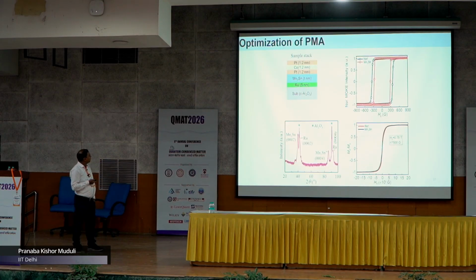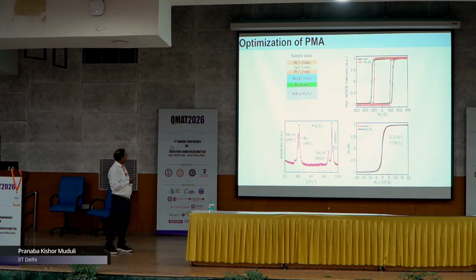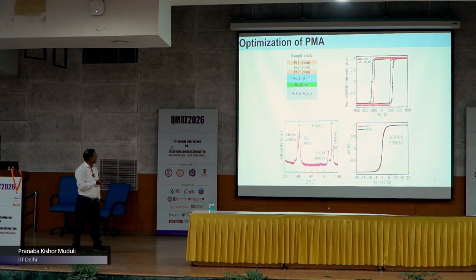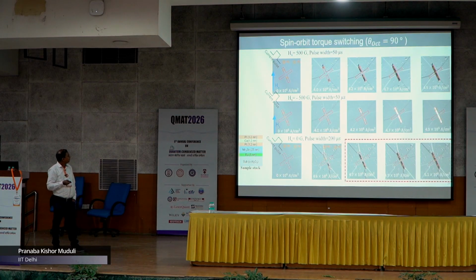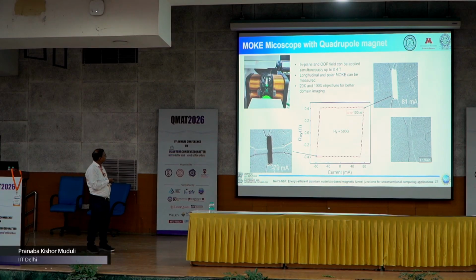Then we wanted to use this for switching, and for that we fabricated a device with platinum, cobalt and platinum. The reason we have platinum at the bottom is that we need the bottom platinum layer to have perpendicular anisotropy of the cobalt. Then we have the top platinum layer to cancel the SOT coming from the bottom. SOT can come from both bottom and top platinum, but they cancel, and then you can look at the SOT from Mn3Ir. We optimized the PMA, and we also checked the XRD and all that to verify the film's quality is good. And then we did the switching measurements, where we now have a very good switching setup in which you can do imaging and transport measurements together.